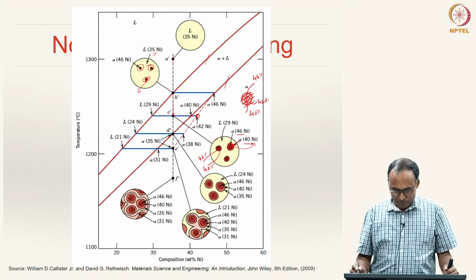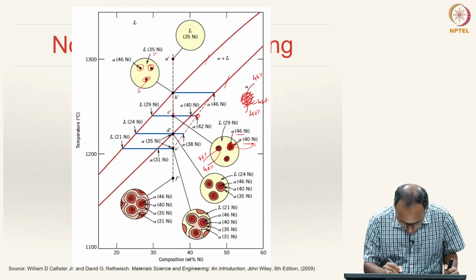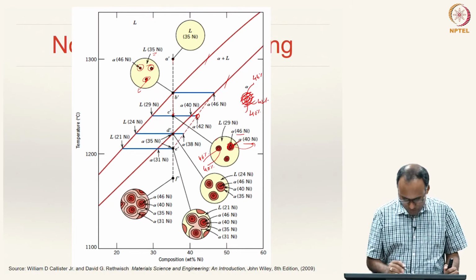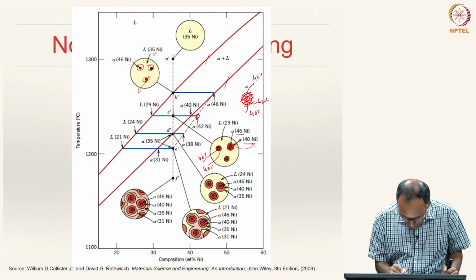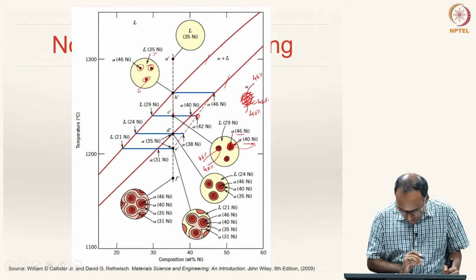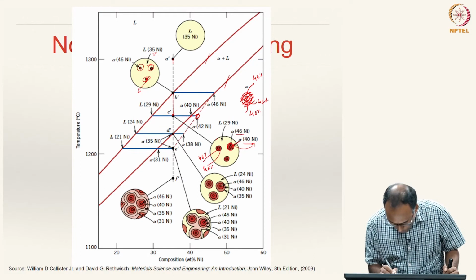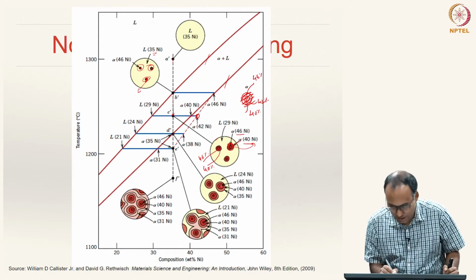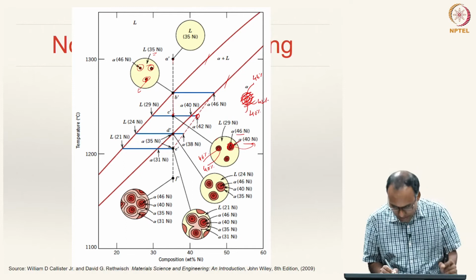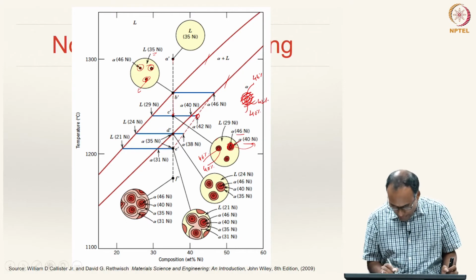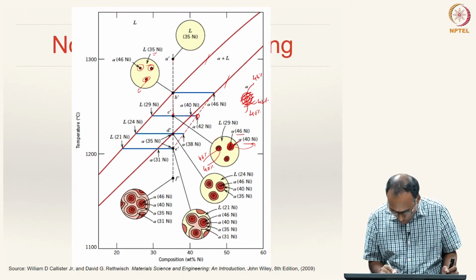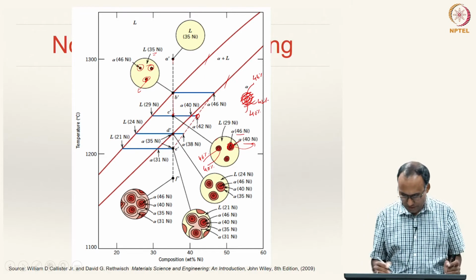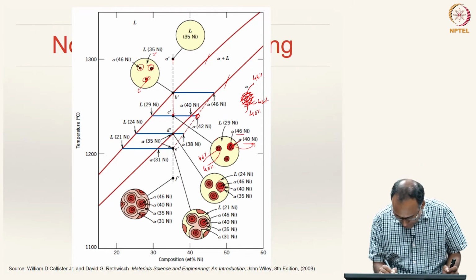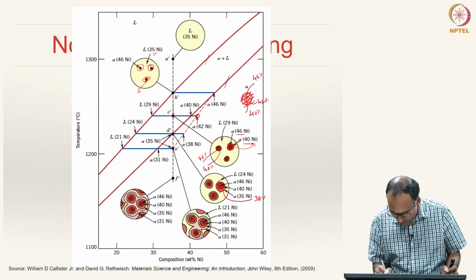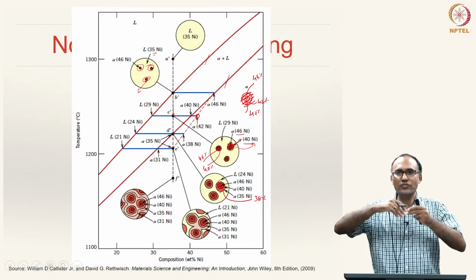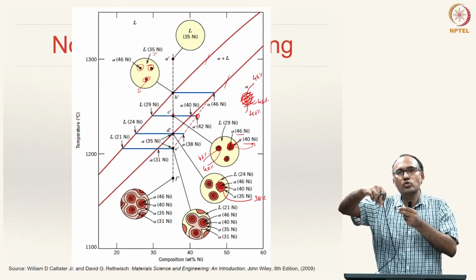All right. And now if you further cool it down, if you are at D prime, again normally you should have 38% nickel, but here also because the center one will still, maybe the center size that is having 46% nickel is reducing, but the next core will have 40 and the next one will have 35% nickel, but effectively this entire thing together will have 38% nickel. So, the phase is not homogeneous from the center to the outer.